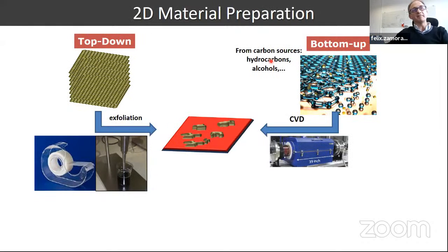But in any case, how can we prepare 2D materials? In principle, you have two alternatives. First, we call bottom-up approaches, which are based essentially on the use of chemical reactions. Of course, you have to do a chemical reaction, but you have to adjust a lot of parameters in order to properly form the 2D structure. Here I highlight the use of chemical vapor deposition, which is particularly interesting for the case of, for instance, graphene. We are able right now to produce graphene using chemical vapor deposition ovens, in which you can use a copper foil as a catalyst, and on top of the copper, at the end of the process, using carbon sources, you form graphene.